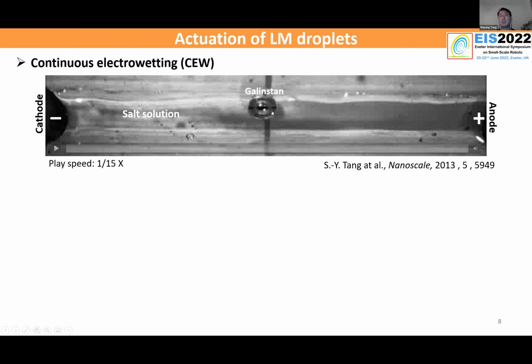I put a droplet of gallium inside a channel which is filled with a solution. The solution can be, for example, a sodium hydroxide solution or a sodium chloride solution. And I apply a potential gradient across the channel. The channel is approximately 10 centimeters long and 4 millimeters wide, and the potential applied is approximately 10 volts.